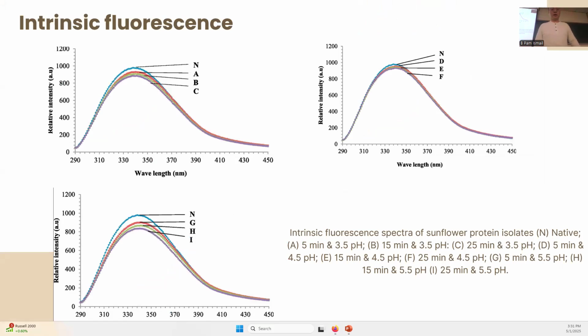Intrinsic fluorescence, we can see a red shift after heat treatment and at different pH values. The heat treatment at each pH value results in a progressive decrease in intrinsic fluorescence intensity. This can be attributed to the fact that heat treatment of protein isolate increases hydrophobicity and subsequently enhances the intermolecular hydrophobic interaction of exposed tryptophan residues, which results in decreased intrinsic fluorescence intensity.